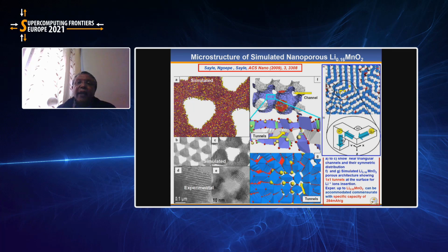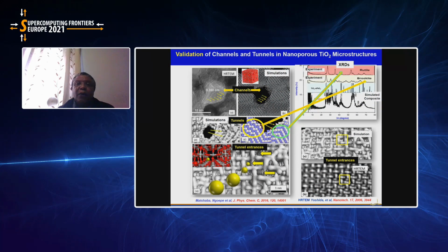of LiMnO2. And here we have a simulated structure which has some channels. And these channels can be seen here. They are nicely symmetrically distributed, but they are equivalent in shape to what we found with high-resolution transmission electron microscope. And here we see the tunnel which the lithium can be able to move inside the cathode.